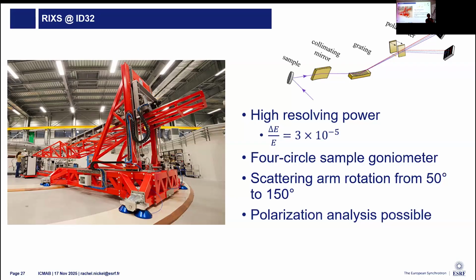Once we orient the sample, we have an automated matrix where you can rotate to any accessible point in Q space, and then we can rotate the spectrometer automatically as long as we interlock. And this means that we can have continuous rotation. It's scriptable. We can run a macro overnight where it's measuring different points. Polarization analysis is possible at this end station, and this is where we have an additional step.